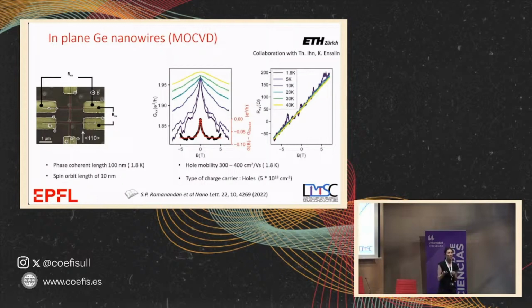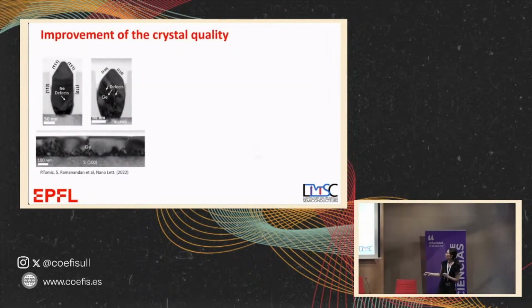So this is the first step towards defining then these quantum dots. Here we have a phase coherence length of 100 nanometers, and we're improving it now with new structures. So how to improve? And so here is the thing. If you want to do very cool physics, you can only do it if you have very cool materials. So the initial wires I showed you were defect-free at the top, but we had some dislocations here. So we had to get rid of the dislocations, so we had to play some tricks.